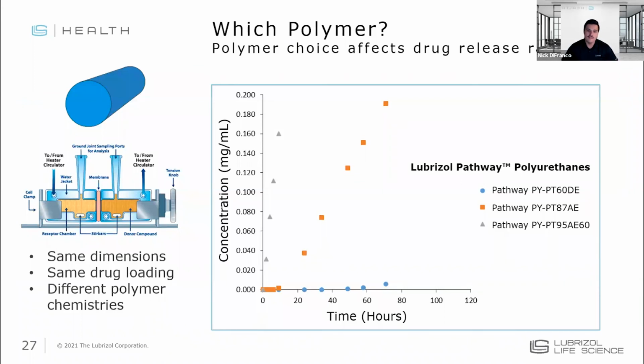And so, looking at how the impact of polymer selection actually affects the drug product itself, we have a case study here. It shows some work we did looking at how our different TPUs produce different drug release rates. We did some in vitro testing using the diffusion cell setup with a donor chamber and an acceptor chamber of drug, same dimensions of the implants, the same drug loading. All we did was change the polymer selection. The three polymers that we selected had different durometers, different hardnesses. One of them had a water pickup, so it actually absorbed water in the body. And as you can see here, we achieved three wildly different drug release rates with the same API.